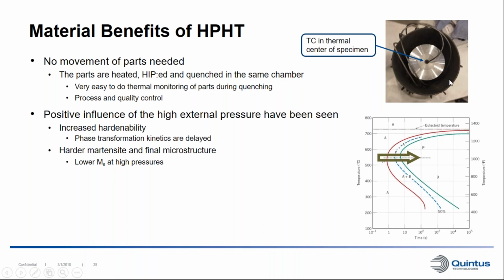So if we look on the upper right here, we have quite a large specimen in one of our smallest lab furnaces. And we can see that we have thermocouples placed in the gas all around the specimen. And in this case, we also put a thermocouple inside the specimen, in the center of it. So we will actually know exactly what cooling rate we have had in the center of that specimen after the cycle.